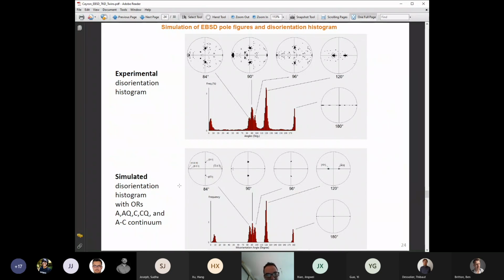On the top, it's the experiments, and at the bottom, it's the simulation. The positions in the histograms are good, the angles are good, and the rotation axes are also in the good positions. So it's a confirmation that, contrary to what is said, you do not have only one orientation relationship, but you have a continuum of orientation relationships. So it's exactly as for martensite: you have a continuum, a gradient of orientation.